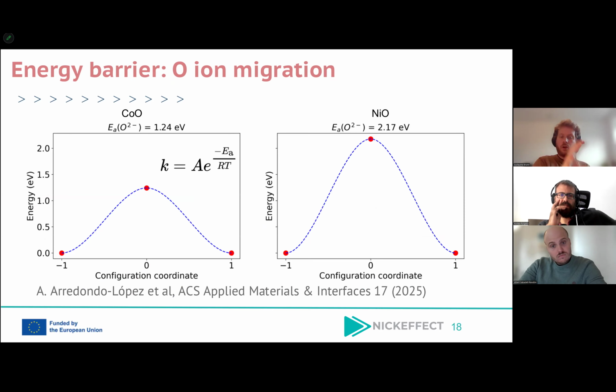So these are the results. Again, on the left, cobalt oxide, on the right, nickel oxide. And so here, the x-axis is the configuration coordinate. -1 means that it's a vacancy at one specific lattice site. +1 is the vacancy at the adjacent lattice site, so just one lattice site next to it.